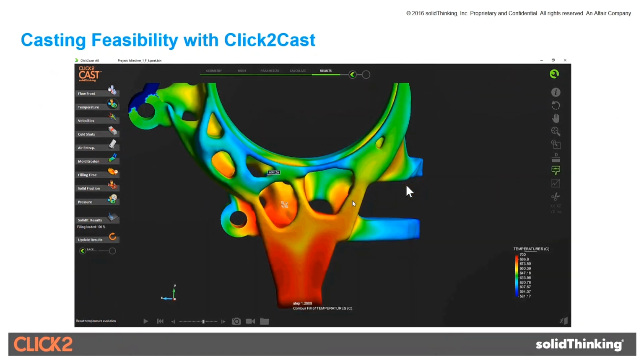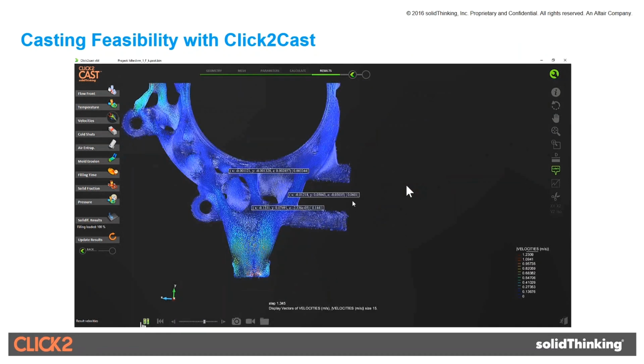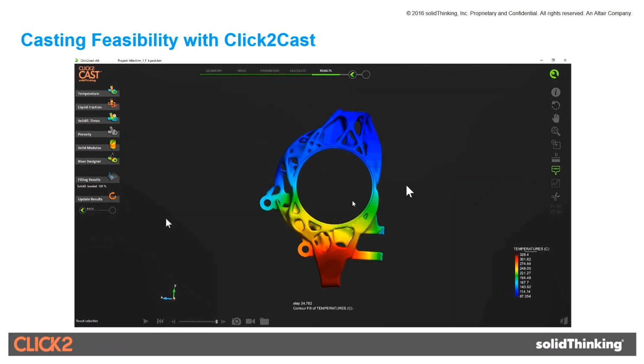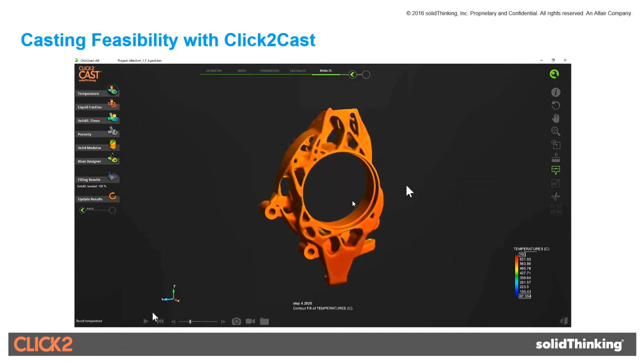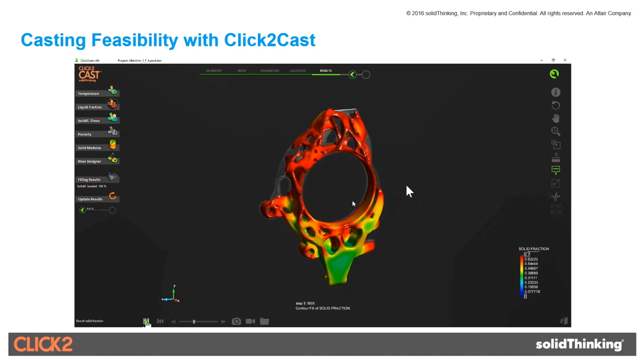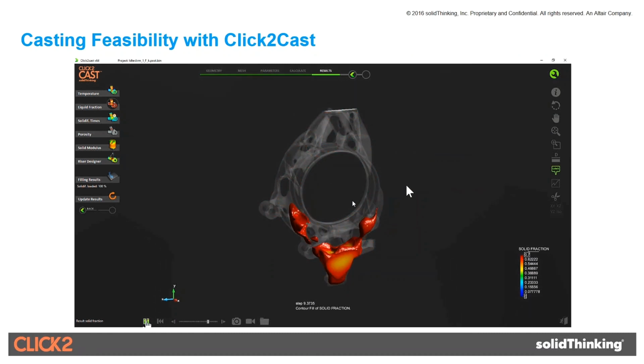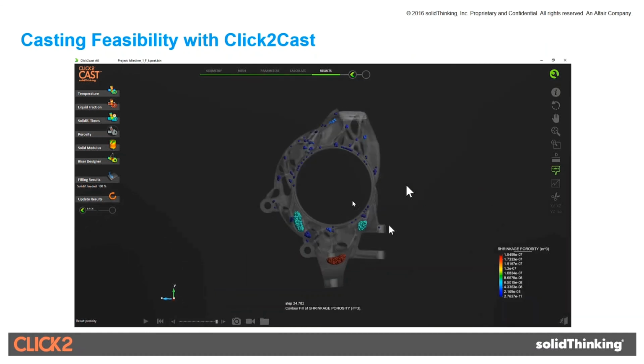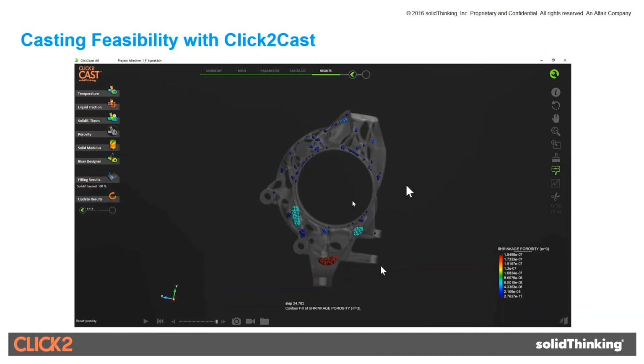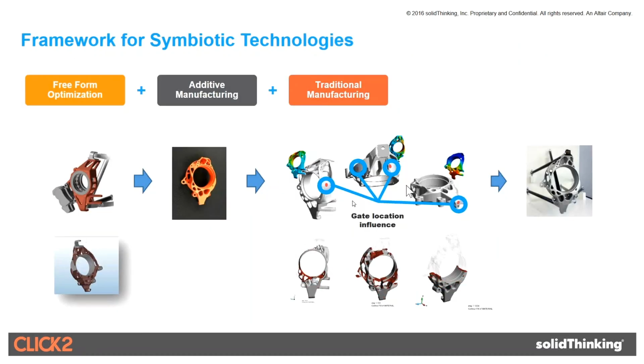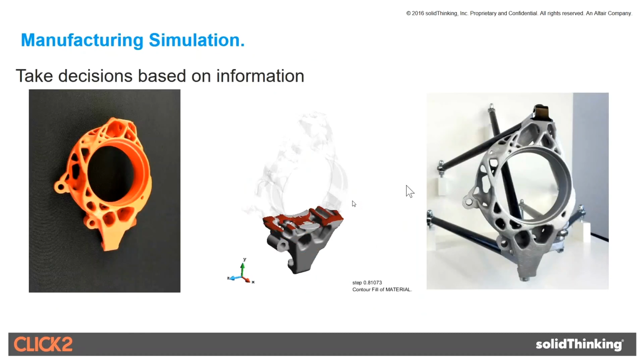And here you've defined the gates. You're defining the process parameters. You're doing the filling and the solidification. It's an investment casting process, which I'll show you in the next screen, and then you evaluate how the flow is. You do both the flow as well as the solidification analysis, and you can see what are the last areas to solidify, how the vectors are while the flow is happening, and you can look at the solid fraction, which is basically the last areas to solidify.